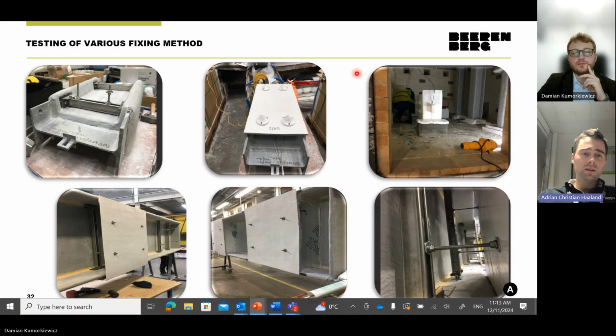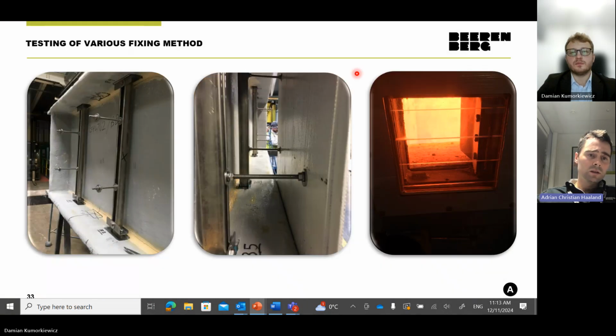Here you see some detailed furnace testing of special fastening methods, bolted studs and tensioning profiles used for a 2- and 3-sided application. We did this to verify that the fastening method would not be adversely affected by the wet applied PFP on the beam, and also by the heat ingress through the bolted connections. A tensioning profile is basically a steel rod which you can tighten to push out against the two flanges and get a secured connection anchor point to bolt on with the panels.